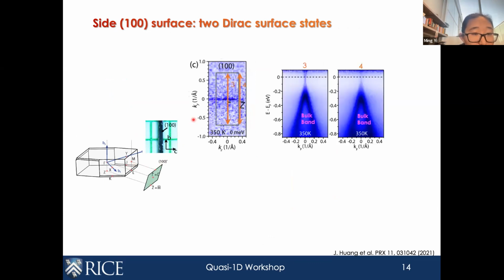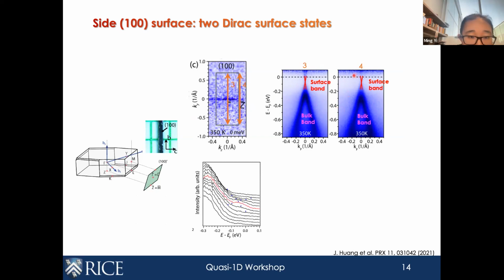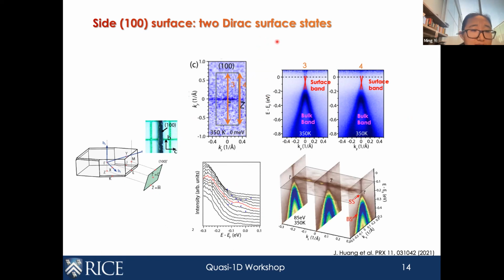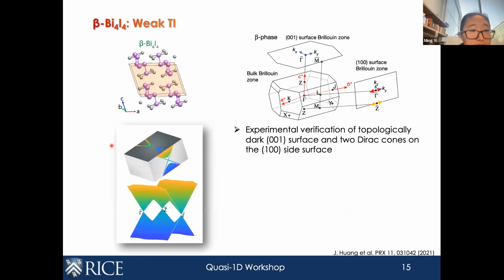Okay. So now, next we want to look at the side surface, which is a more interesting one. On the 100 surface, if we take a look at the band dispersions here in the middle on the side, I won't go into details, but these are actually the bulk bands. And then within the bulk gap, you can see here are the surface states, surface Dirac crossings. And if we look at the EDCs here, in the middle of the band, we can see that this is consistent with a gapless surface state. So we can understand that, therefore, we observe two Dirac surface states on the side 100 surface, and no topological surface states on the top. And this would qualify it as a weak TI.